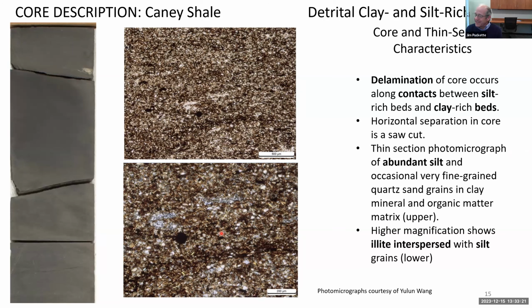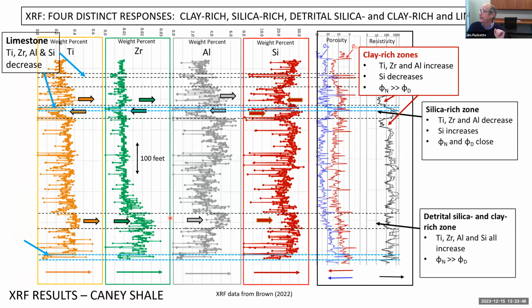And the higher magnification shows that clay, mostly illite, is interspersed with the silt grains most of the time. But in some cases, we're seeing quartz to quartz contact, and we're seeing some brittleness starting to be imparted to this rock. And this will have an influence on the log characteristics and also on the elemental concentrations, which we'll see in a minute. So here we go.